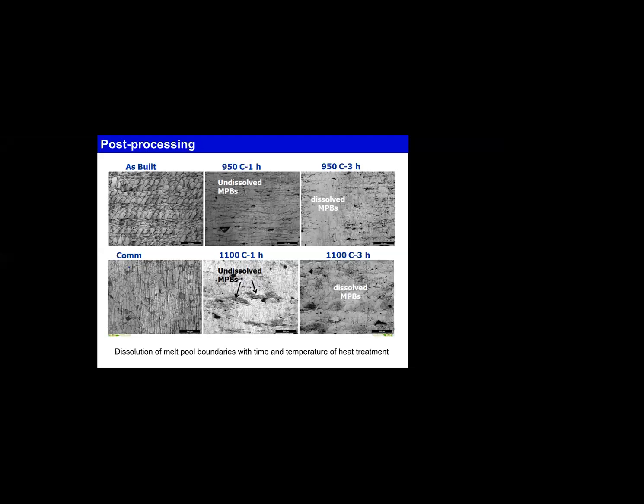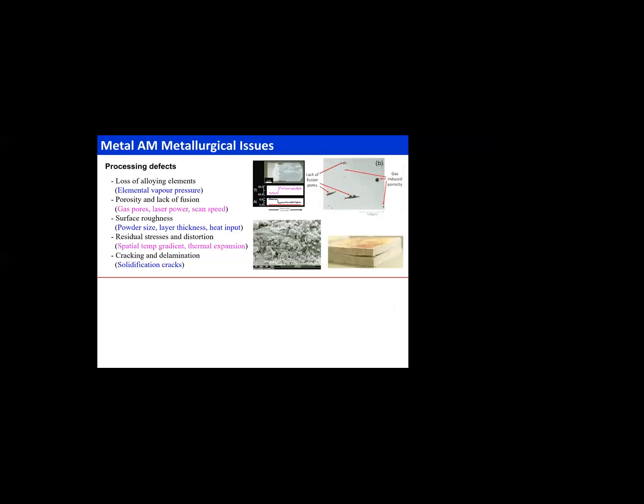Now I come to a brief on AM metallurgical issues. What are the processing defects? You can see, there can be loss of elements. All the elements which have low melting point may evaporate from the bed, and finally your composition may not be what you want. And there may be some porosity or lack of fusion. There may be some gas entrapment in the material during melting, or as I showed you earlier, some powders may not be fused altogether, or may not be properly sintered.